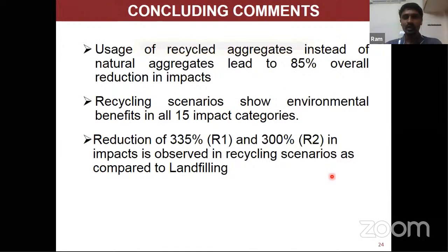Concluding comments: recycled aggregates lead to 85% reduction in the overall impacts as compared to natural aggregates. Recycling scenarios show environmental benefits in all 15 categories, and a reduction of at least 300% in impacts is observed in recycling scenarios as compared to landfilling scenarios. For detailed data and reading, you can follow the journal paper that we have published in a production journal, as well as the chapter.